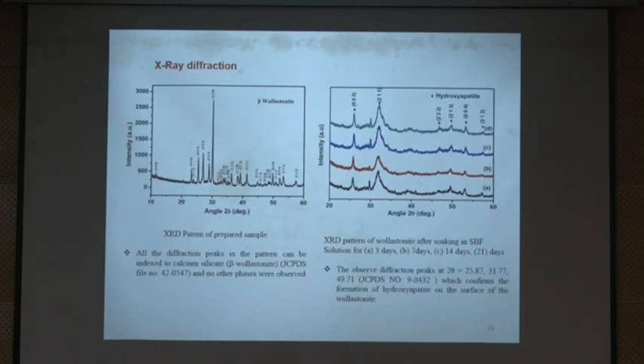So this is the XRD, right, without immersion. Remember, the previous one is glass, we got the amorphous structure, but now it's crystalline, it has some structure. We compared with the JCPDS data, it indexes with that number, and the structure is beta wollastonite. So we have different structures, anorthite, wollastonite. I'm talking about calcium silicate, right. So this is the structure of the calcium silicate you have prepared, and then we want to check whether the material is active or not.